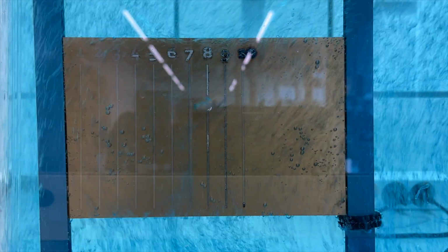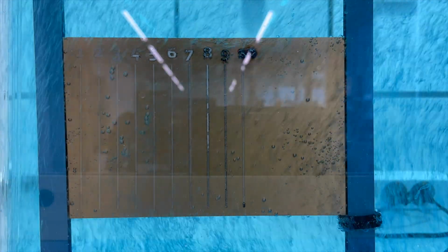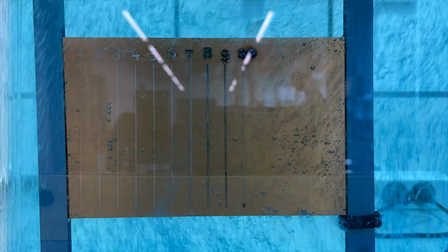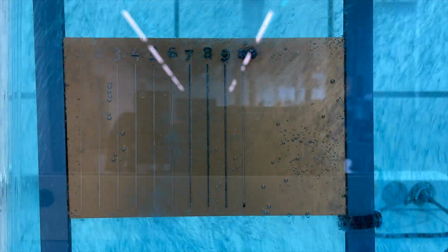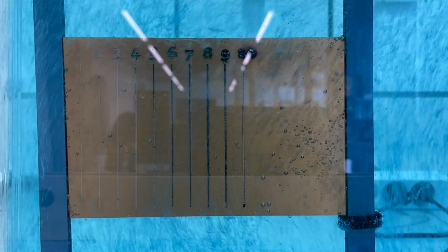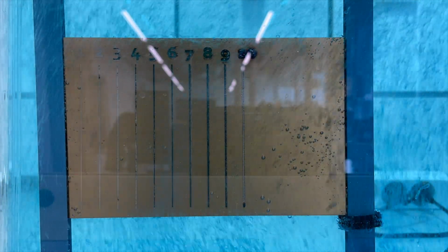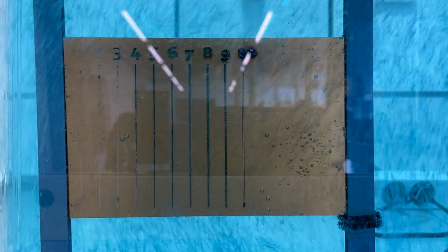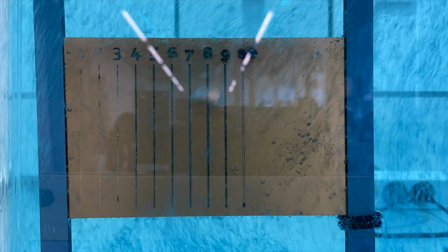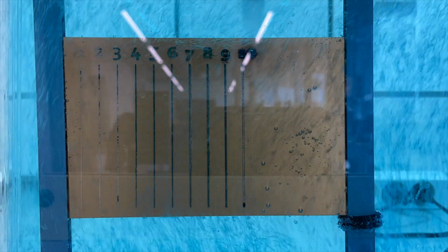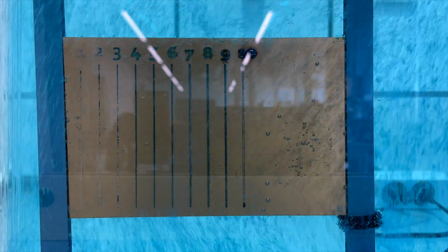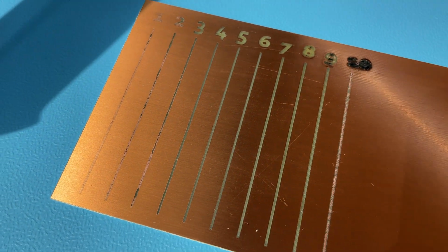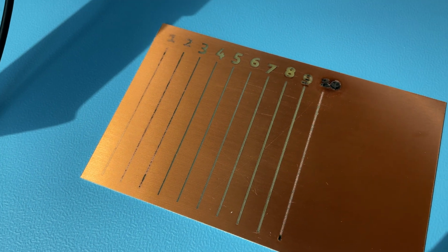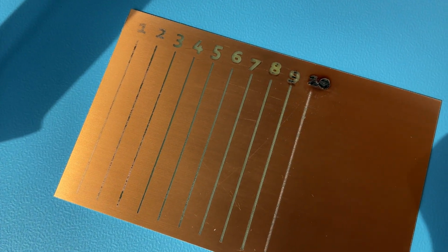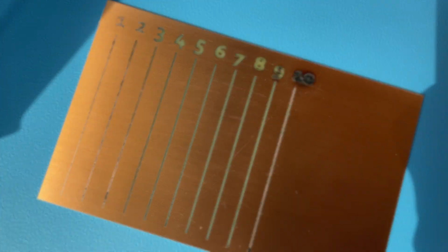Afterwards we went for etching. This is a time-lapse of the whole etching process, and if you take a closer look at number 7, 8, 9, and 10, you will see that the copper is already changing and already gone at this moment, and we can barely see the yellowish greenish color of the core material of the circuit board. Also number 5 and 6 are looking good. Number 4 is also clearing up a little bit. This was in total 30 minutes, so we really took our time to give every part a chance to clear up. In the results, we can see that from 4 on, we have very good results, and even number 1, 2, and 3 have partially etched areas, and surprisingly, number 10 did not perform very well.